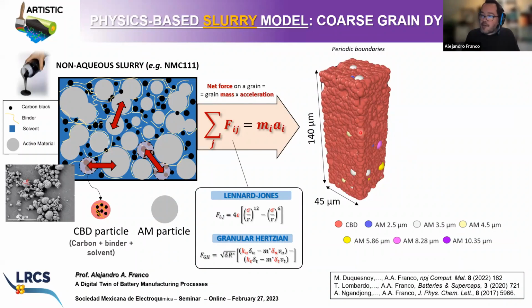And here, in red, you see the CBD particles containing, once again, carbon, binder, and solvent. The other particles with different colors correspond to the active material particles having different sizes. So the input of this model is going to be the formulation, that means the ratio that you have in weight percentage between active material, carbon, and binder. Another input will be the particle size distribution of the active material.